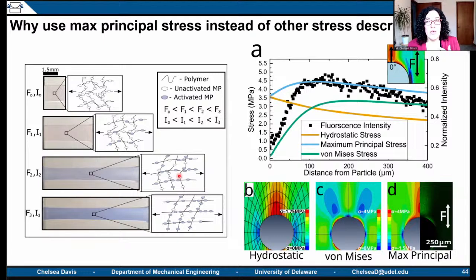So even though we're applying a global uniaxial tensile deformation, we're going to have a huge amount of activation arising from shear that is coming from Poisson effects. And in fact, that's why we see such a bright response right here at the interface of our material. We see this, which can only be a result of really high shear stresses. We have thought deeply about this.